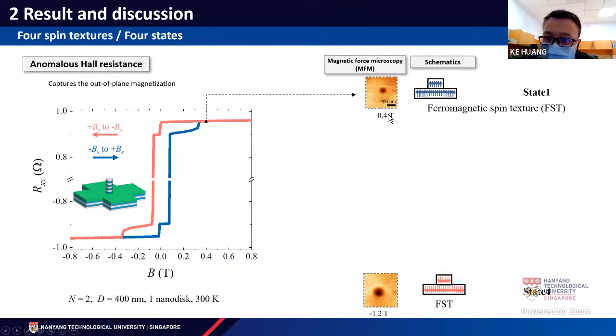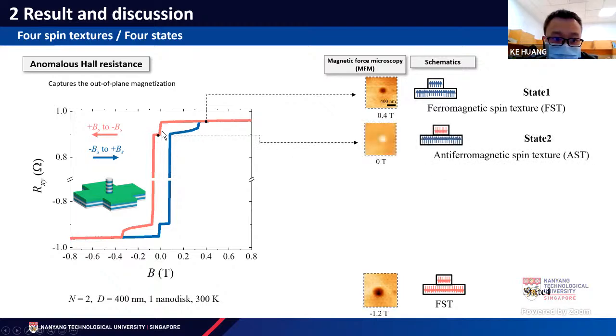What MFM tells us is that if the nanodisk and the bottom layer have spins along the same direction, it gives you a dark color. Otherwise, it gives you a relatively bright color. At 0.4 Tesla, all the spins are upwards, so the center is dark. Similarly, at negative 1.2 Tesla, all the spins are downward, so it is dark. If we sweep it, after it crosses the first switch, the top spins are flipped. So it becomes antiferromagnetically coupled, and the center becomes bright.